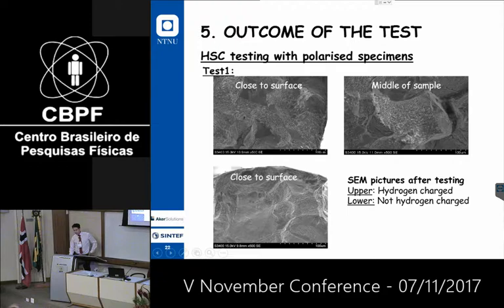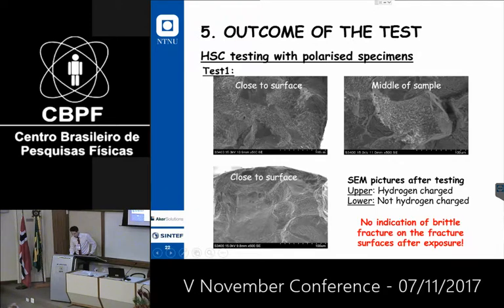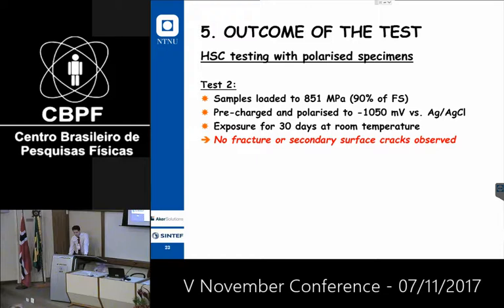Here we have, after HISC testing, the upper two images hydrogen charged, and the lower not hydrogen charged, and there is no indication of brittle fracture on the fracture surface after exposure. This is further evidence that we don't have HISC influencing this. So the samples loaded to about 90% of fracture strength, pre-charged, exposed for 30 days at room temperature in artificial seawater, showed no fracture or secondary surface cracks.